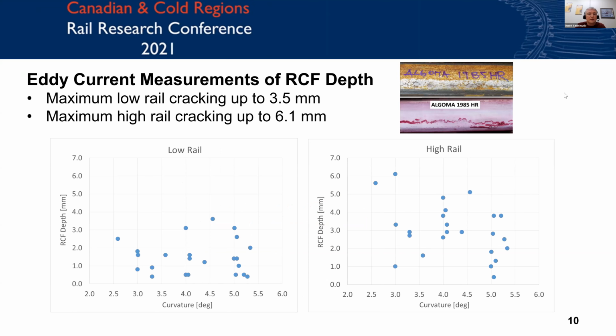So one of the things that we did during the visit is we had an eddy current with us, and we measured the depth of cracks of the rails that are currently in track, and compared those numbers to the rail that actually led to the critical failure. And if you remember, I showed you in the first slide that the rail shown here in the image is from the critical failure. That crack right there on the gauge face side corner of the high rail was between 4 and 5 millimeters in depth. Well, looking at the high rail specifically, between 3 and 5 degree curvature, some of the cracks that we saw in track went up to 5 millimeters, and for the 3 degree, one crack was even 6.1 millimeters. So that's obviously concerning, that you have a fairly high population of those types of cracks in track right now in that railroad, and this is something that should be looked at.